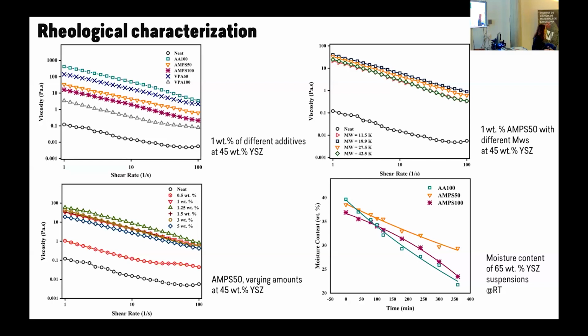So that is why we do rheology. And here, as you see, we are looking at the particles at 45 wt.%. And here, we have all these polymers that we would like to try. If you are around this range, you don't get a dough, you get an ink, which I will be talking about. In order to get dough-like rheology, you should be around here. And among those, we have chosen this AMPS 50. And here, we are varying the amounts of AMPS 50.